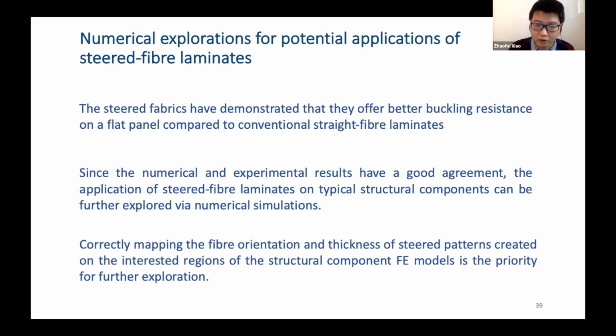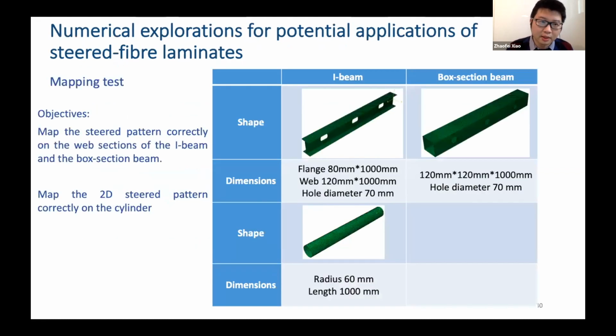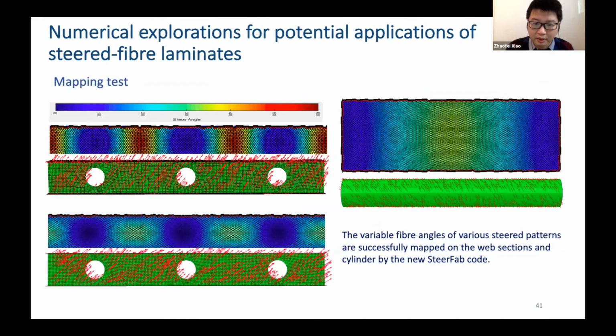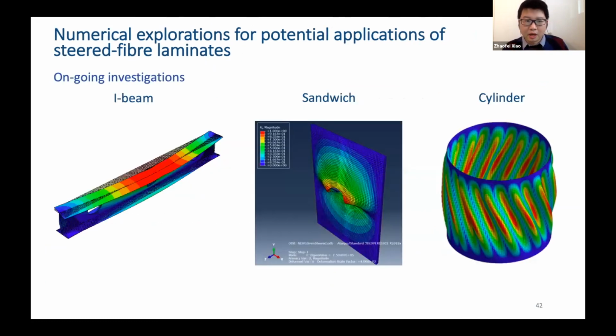But the first step, we need to make sure our mapping of the fiber orientation and the thickness of the fabric is correct on the numerical model. So to test that, we did a mapping trial. We want to map the steered pattern correctly on the web section of the I-beam or box beam, and also map the 2D steered pattern correctly on the cylinder. So here's the result. We can see the fiber orientation of the steered pattern we generated is correctly mapped on the finite element model in Abaqus. Now, Lee and Paul, the two new research assistants, are still doing the investigation about the optimization of the mechanical properties on the I-beam, sandwich structure, and cylinder.